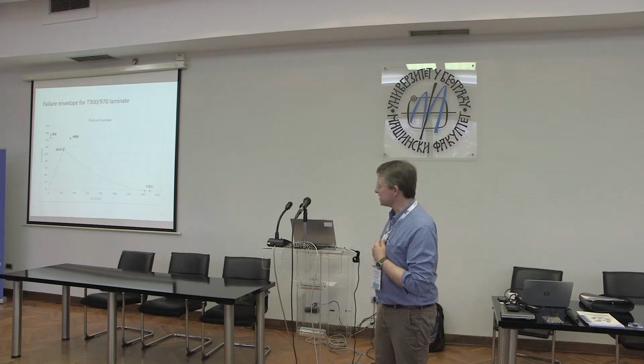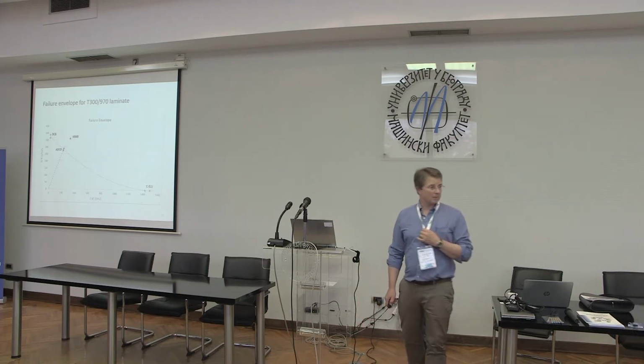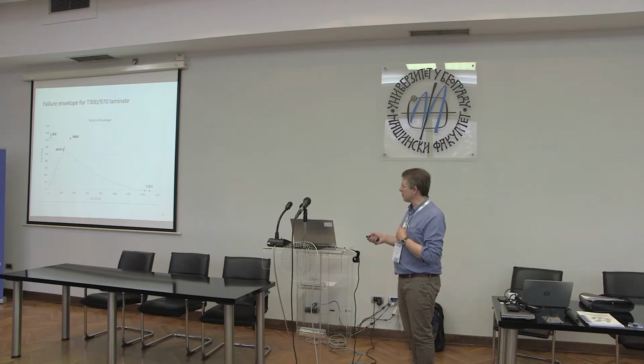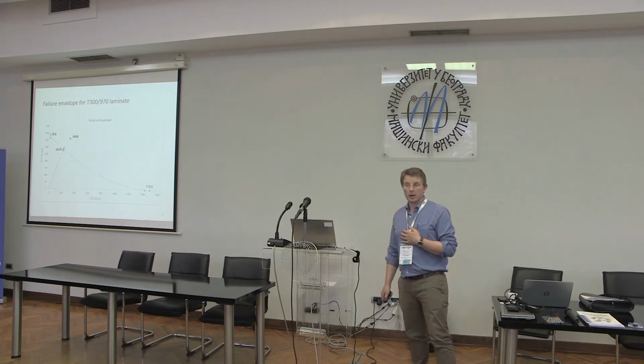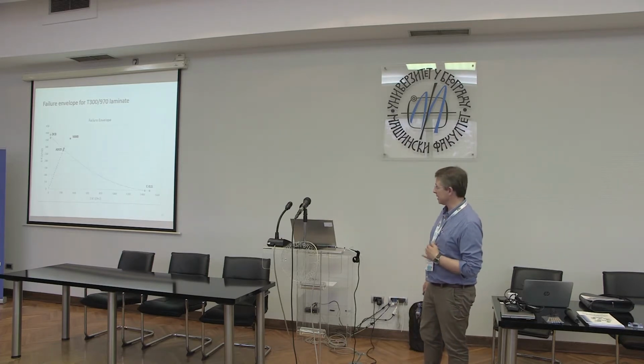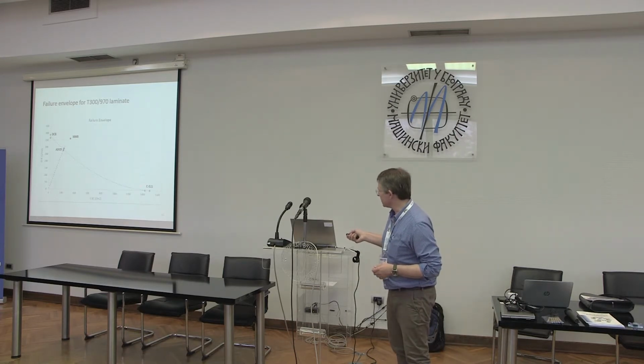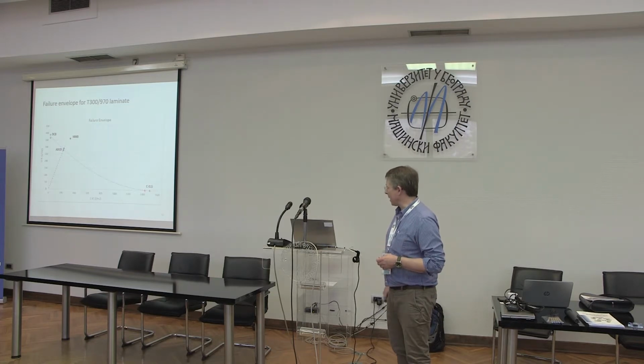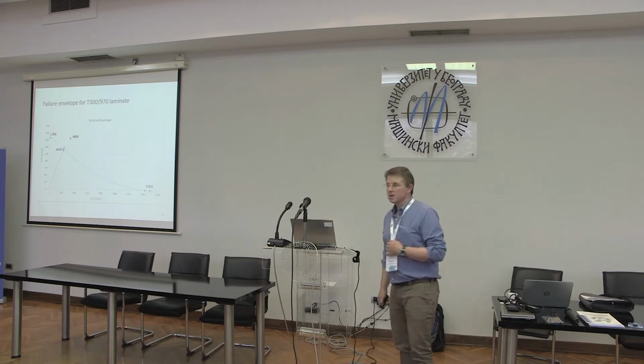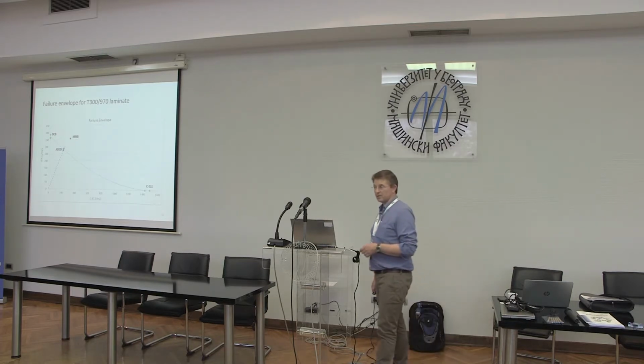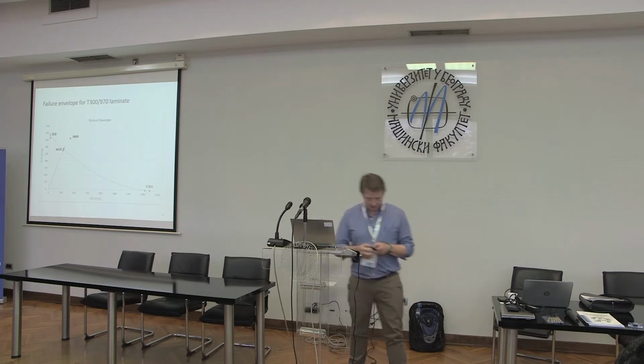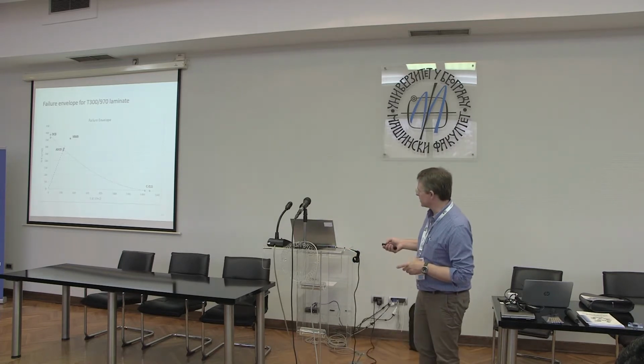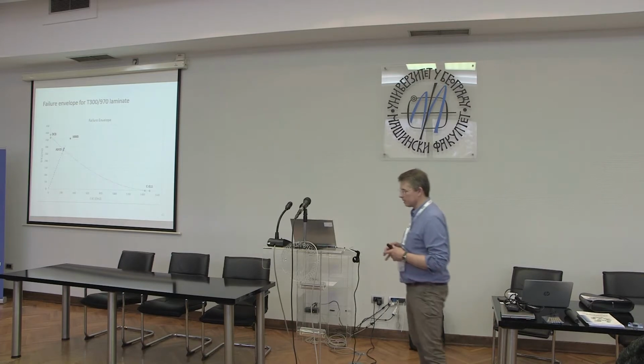You might pragmatically want more data points. Using the ASTM mixed mode bend, you can fill in points along here. 3 points gives you a quick yardstick as to how the material is behaving in the 1-2 mode. So you can see for this one, we had a mode 2 fracture resistance of about 1400 and a mode 1 of somewhere between 300 and 400. So that was our sort of factor of 4 to 5 in this material, and you can see that our mixed mode value fell on that particular failure locus.